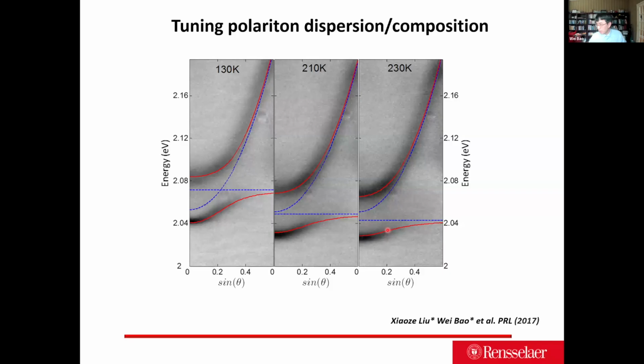However, we never saw a Bose-Einstein condensate in such a system, even though we made as many as 600 samples and could have a Q factor as high as 1,500. Unfortunately, we never saw a Bose-Einstein condensate due to the intrinsically low quantum yield of this WS2 material, tungsten disulfide, because the quantum yield in this material is typically 10 to the minus 4. That essentially means you shine a laser with 10,000 photons, and then you only get one photoluminescence photon emitted out.